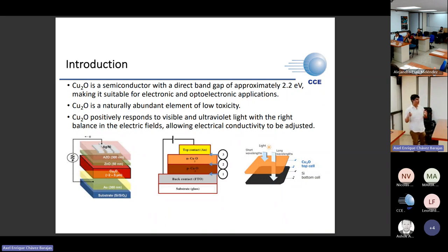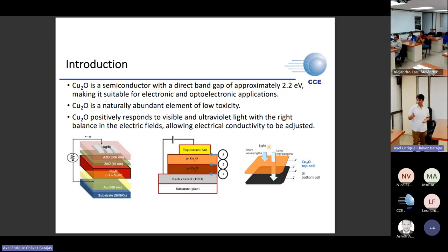in this process, we can control the thickness of the film in a very wide range. I can obtain films between 15 nanometers and more than 2 microns, just by changing the copper source, the temperature, and the amount of triethanolamine. I consider that these films are suitable for other applications, for example solar cells. I don't know if I mentioned it before, but we can turn the conductivity of the material from p-type to n-type. So at least with this method, we can produce, for example, a homojunction.